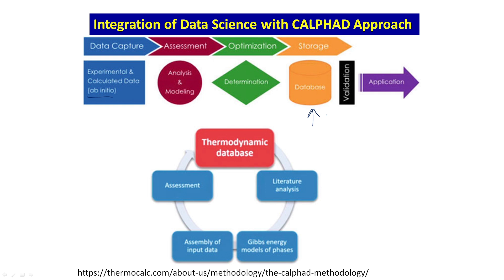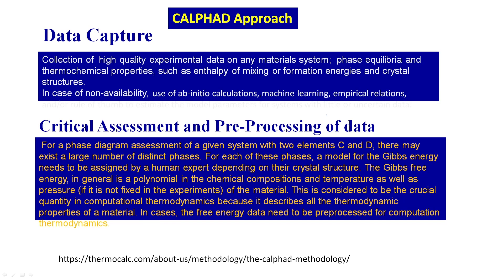Input data essentially provides free energy models of the phases. The first step is data capture — in CALPHAD, data is the key thing, without data you cannot do anything, similar to machine learning. Data capture is the collection of high quality experimental data on any material system: phase equilibria, thermochemical properties, enthalpy of mixing, formation energies of phases or compounds, or crystal structures.